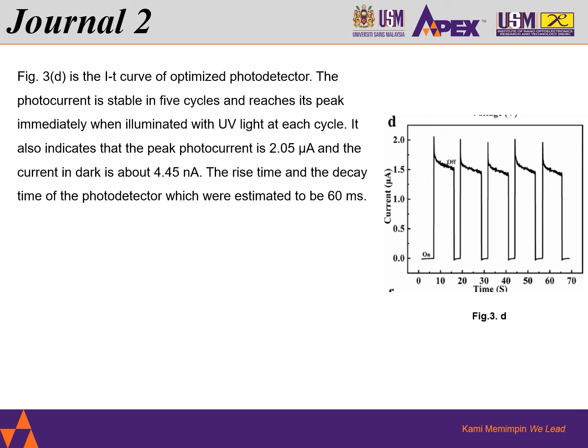Now figure 3d is the I-T curve of the optimized photodetector. The photocurrent is stable in 5 cycles and reaches its peak immediately when illuminated with UV light at each cycle. It also indicates that the peak photocurrent is 2.05 microampere and the current in dark is about 4.45 nanoampere. The rise time and the decay time of the photodetector were estimated to be 60 milliseconds.